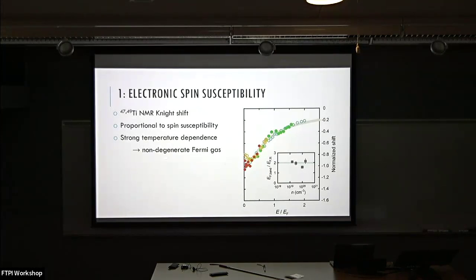And what you get is that this Fermi energy is half the band Fermi energy. So if you do the band structure calculation, you get a Fermi energy, and what you get from experiment is half that, which means that the mass is enhanced by a factor of 2, which has been seen before at low temperatures. But now here we show that there's basically no temperature dependence. So you could not get a nice collapse like this if the effective mass were really temperature dependent. So the message here is that, yes, there is a mass enhancement, but it doesn't depend on temperature.